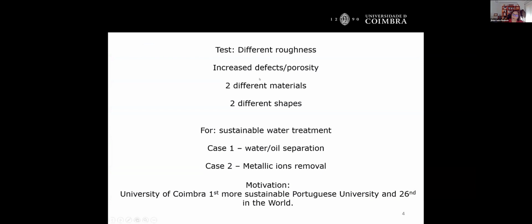This work was a challenge, because all my colleagues are always telling me, yeah, additive manufacturing, but that's a lot of defects. And really, I was a little bit sick of hearing them. So I tried to take advantage of a problem, which means that I would not face it as a problem. I would take advantage of that problem. So I tested different roughness with increased defects, in this case porosity, with two different materials and two different shapes.